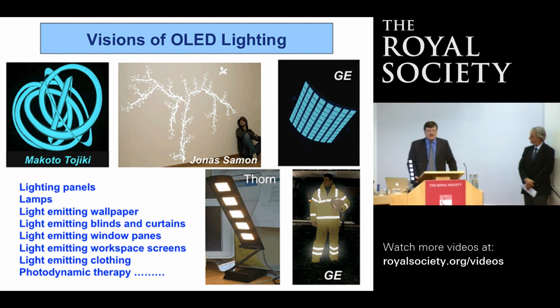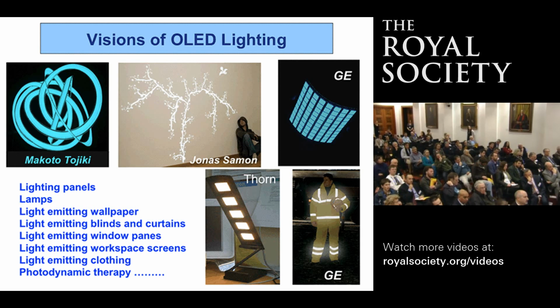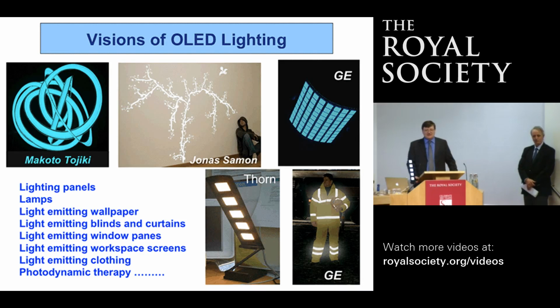Now, typically for display applications, the device structures are encapsulated. That is principally to protect the electrode, in particular the cathode, which is used for injecting electrons, from moisture. Typically those cathodes are made from reactive metals, lithium, barium, calcium, those sorts of metals, and they obviously degrade very fast. If you do that encapsulation, then people have been able to make display devices where the light-emitting diodes have lifetimes in the 300,000, 400,000, 500,000 hours range. So under normal use conditions, 5 years, 10 years type of lifetimes. The lifetimes are not actually that bad. There's still plenty of work to be done, and people are still doing a lot of work to address that issue, but it is possible.